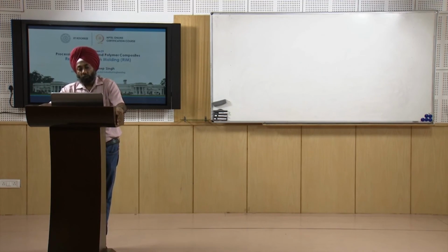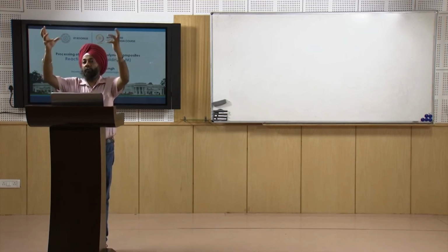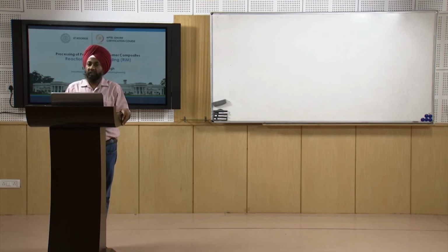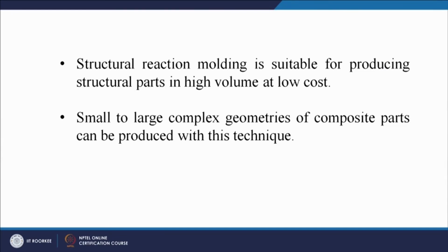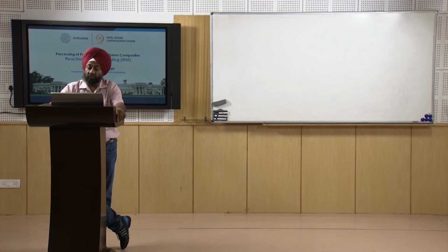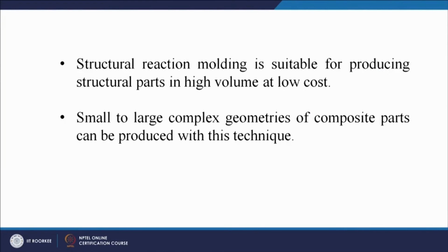In reaction injection molding, no heat energy is required and mold cost is also low. Now why in reaction injection molding? Because the polymerization takes place because of the reaction of the two ingredients or the two constituents that are coming from two reaction chambers, and the process is exothermic. So the heat of the reaction helps in the curing process, and no additional heating system is required as in the case of the conventional injection molding process. Structural reaction injection molding is suitable for producing structural parts in high volume at low cost. So that is another advantage which is specific to structural reaction injection molding. Small to large complex geometries of composite parts can be produced with this technique. So the complexity can also be achieved with the reaction injection molding process.